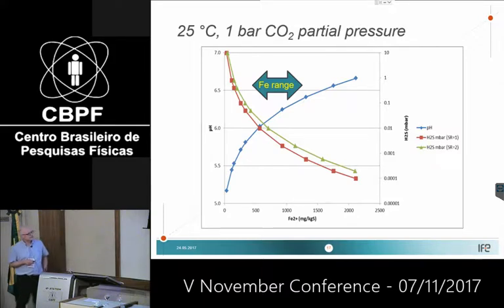And that means that if you have a system, you have a certain amount of iron, which gives you a certain pH, and you are in this range of corrosion product, it's then not possible to have a higher H2S partial pressure than 0.01 or close to that. Without consumption, it could be several millibar. But when you have consumption, it's not possible. And that is very important when we talk about both lifetime extension and possibility for cracking of high-strength steel.